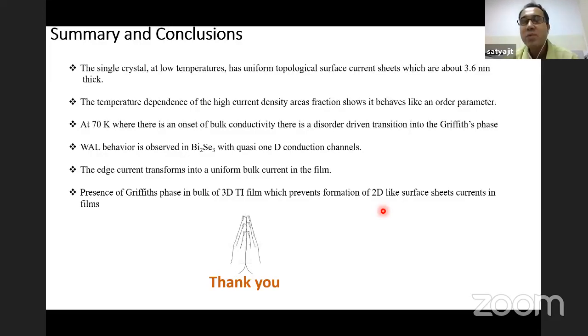I see. And the initial data that you showed on the superconductor was what, niobium diselenide or? No, this is a potassium doped barium iron arsenide that we have recently published in PRB. I see. Because one thing that I was curious to know in the data, you have a significant amount of current which is also flowing in the bulk. Yes. Why is that? Normally, you expect the current to flow within the penetration depth on the surface. But actually what happens in this system is that as you increase the temperature, we have looked at this close to the melting transition. There is a melting transition in this system.